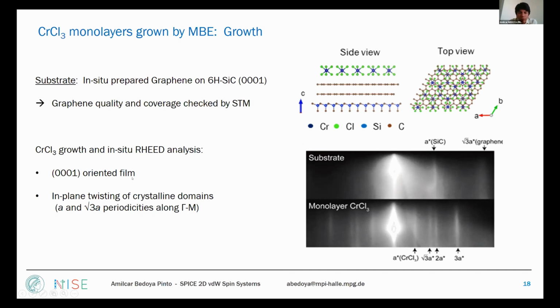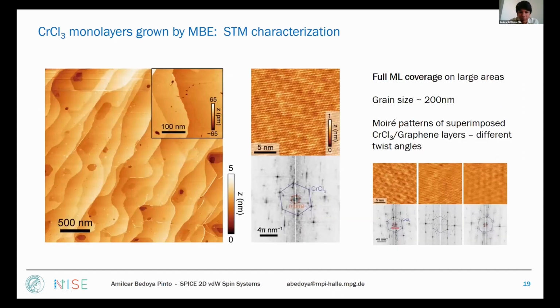And that's one important thing to mention here. The film is nicely 0001 oriented. That's how we would expect it. But inside the plane, it has an in-plane twisting of domains. So that means that when we look along one high symmetry direction, we can see the lattice parameters of the hexagonal lattice for both center to edge and center to side directions. So that means that we don't have a purely single crystalline orientation inside the plane. That will be very important for the interpretation of the magnetic properties.